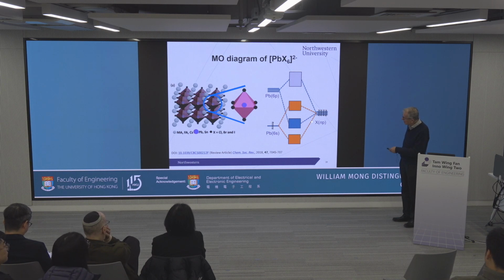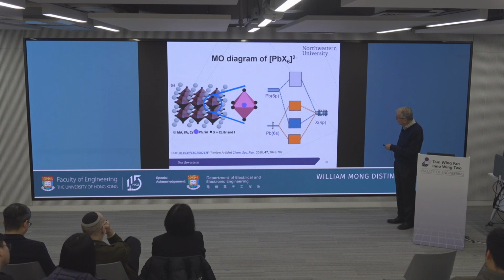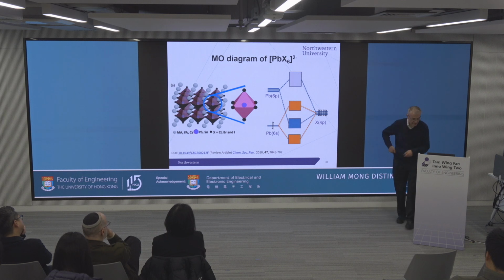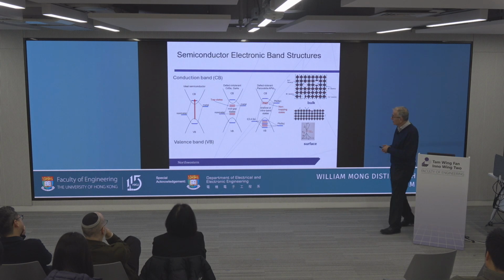But this is not really a good interaction because everything is filled, this is full of electrons, this is full of electrons. This is antibonding, this is bonding. But you don't get stabilization because the antibonding is also filled. Stabilization comes from this interaction where this is empty; they interact, these electrons form this band, energy goes down, antibonding is empty, goes up, and you have a stable compound. However, the highest occupied state is this because of these electrons, and the lowest unoccupied state is this. So this is the HOMO-LUMO gap, and this is the band gap too. If this becomes a solid, this would be the top of the valence band, and this would be the bottom of the conduction band. And that's important.